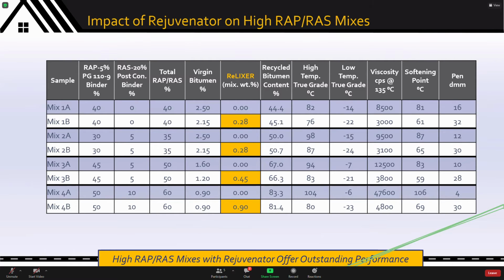So what happens to the extracted bitumen? As you can see, the addition of ReLIXER helps dramatically improve the viscosity profile. From an 8,500 centipoise viscosity at 135, you're able to go to about a 3,000 centipoise bitumen. It helps to improve the low temperature properties, moves it to a -22, which is much more common with paving grade bitumens, and also the associated pen properties that you can see here, bringing it more in line with the 25 to 30 pen material commonly used for paving across the globe.